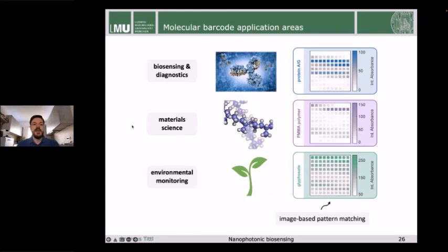So we apply this technique to three different fields of sensing. I already showed you biosensing and diagnostics with the protein AG barcode. We did material science by looking at PMMA polymer, and you can see that the response is actually quite different here. And then finally, environmental monitoring by looking at glyphosate pesticide. And you see that already with your eye, you can do image-based pattern matching to differentiate these three kinds. And if I show you now an unknown barcode, you would probably be able to already tell me if it's more of a protein, more of a polymer, or more of a pesticide.